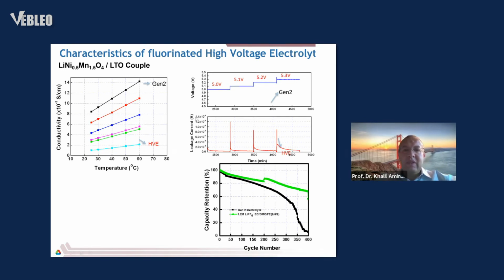is high conductivity. We did a floating test. As you can see here, we don't see any leakage current until 5.2 volt. And we've taken this chemistry, which is high voltage, 4.8 volt, and run it at high temperature. You can see with the conventional electrolyte, the capacity dropped to 0 after 400 cycles. With this new electrolyte, we sustained significant capacity retention at these high cycle ability.